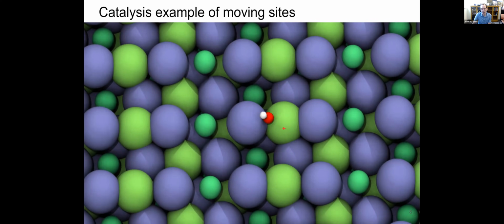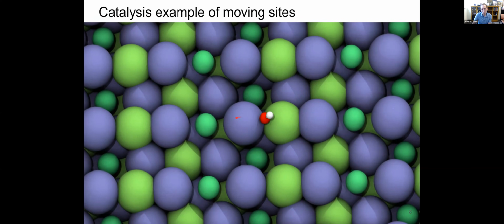We see there's three different types of atoms: little green, big purple, and this OH. It's a relatively straightforward calculation. We guessed that it was sitting sort of on top of the green. We did a number of steps with our favorite electronic structure code, and we saw that the OH moved a little bit going from the green to the purple. And even this super simple local relaxation often takes something like 1 day or 2 days on a really fast computer at something like DOE NERSC, the Cori supercomputer.